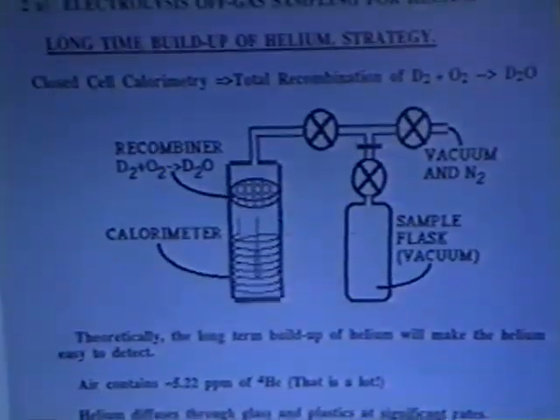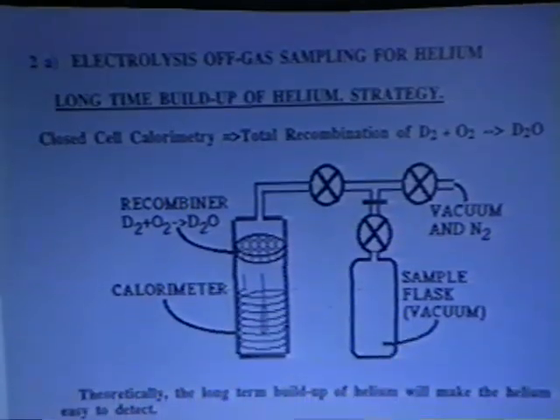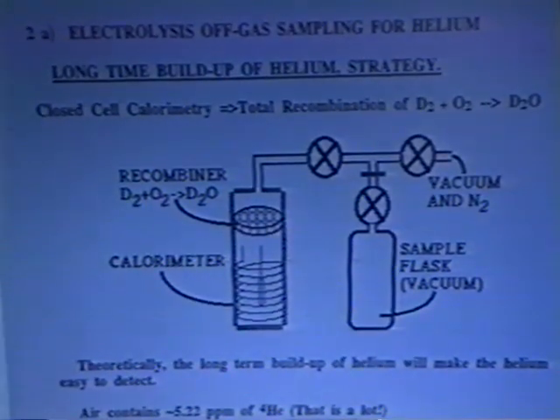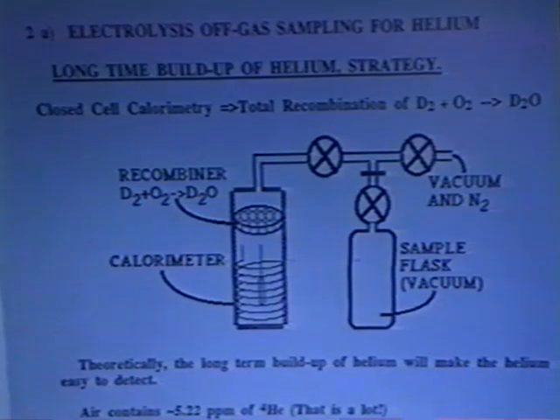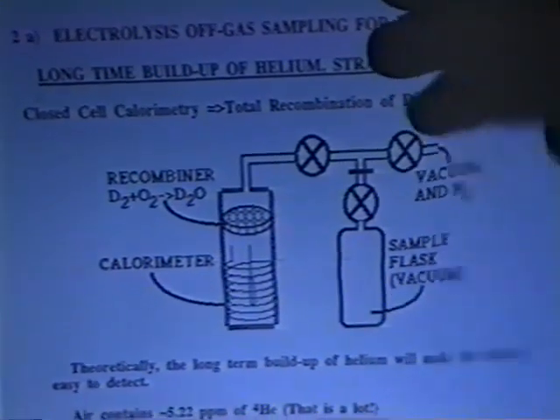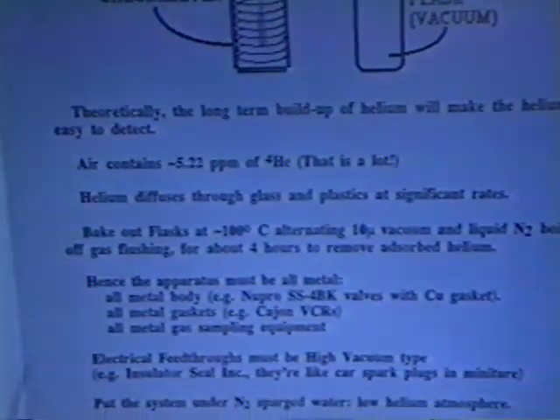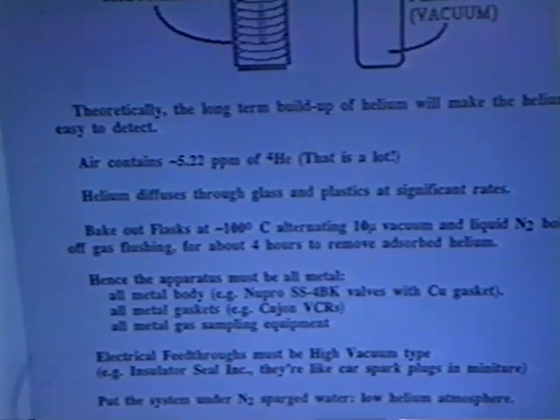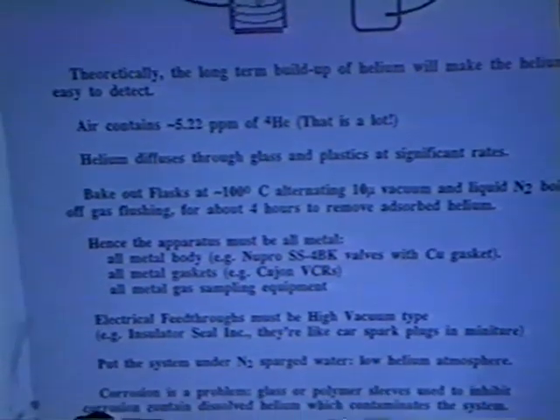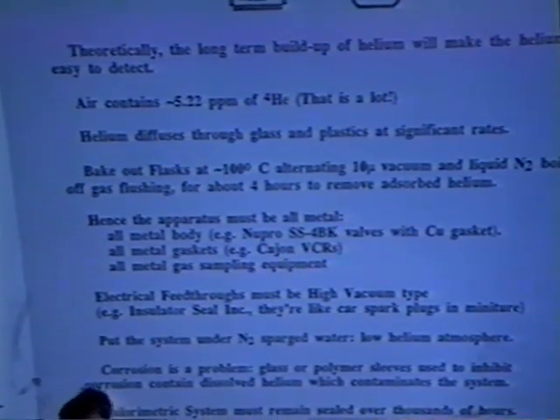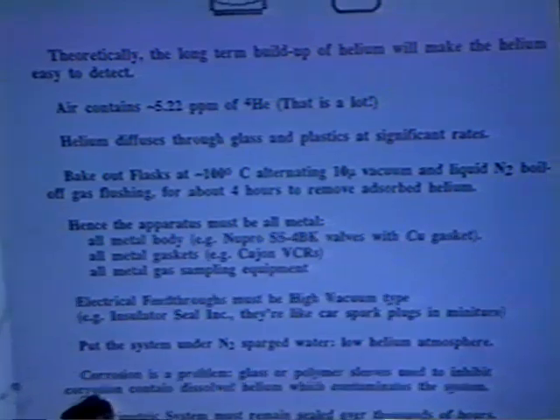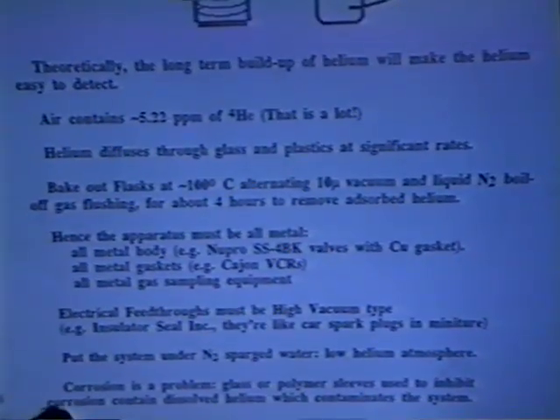You can play tricks, like you can put your calorimeter and gas system underwater and bubble nitrogen through the water to get rid of the helium in the air, because there is no air in there. You've sparged it out. But you've got problems inside the calorimeter because you've got corrosion, so you've got to put in glass sleeves or plastic sleeves, and they'll entrain helium, bring it into the system, and it'll diffuse out into the system. Hopefully that would be a small problem.